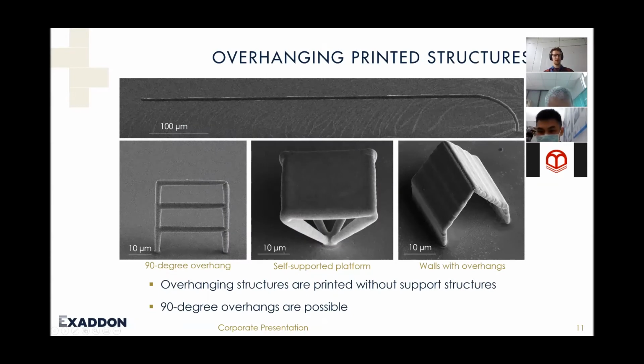So our machine prints at room temperature, and it doesn't require support structures, which is very unique, particularly within metal additive manufacturing. The top image has an aspect ratio of about 100:1, and this is entirely self-supported. You see in the lower ones that 90-degree overhangs are possible, and there's no need for support.